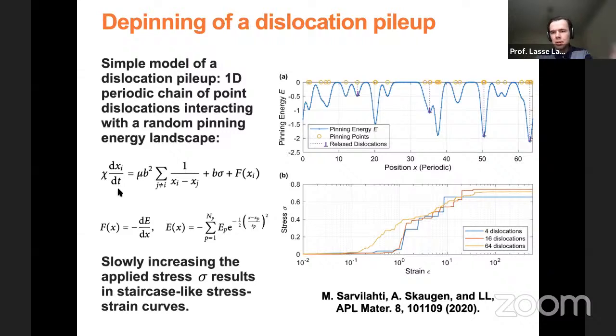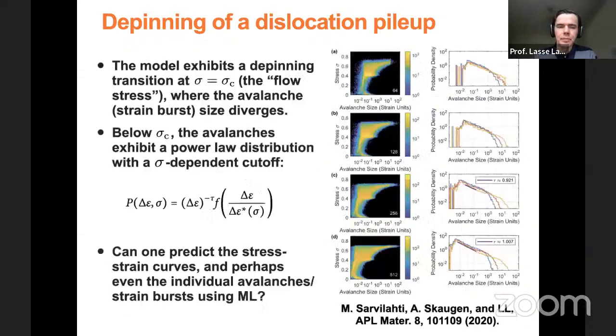Here we can again, in the same way as before, simulate this model. So we integrate this equation of motion numerically, and we can generate stress-strain curves that look like this. So you again have these avalanches of plastic deformation there. Different samples will again look a bit different because each sample will have a different realization of this pinning energy landscape.